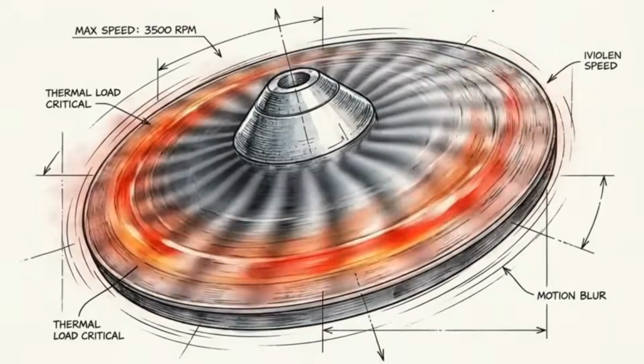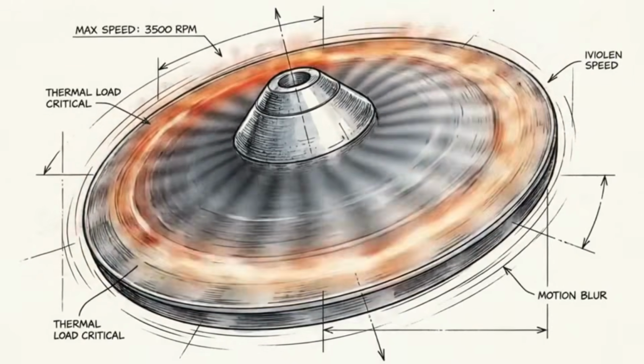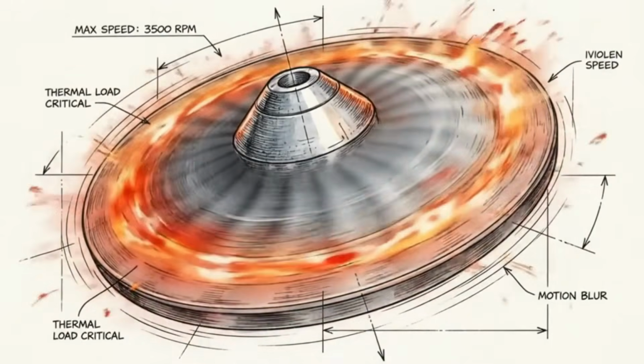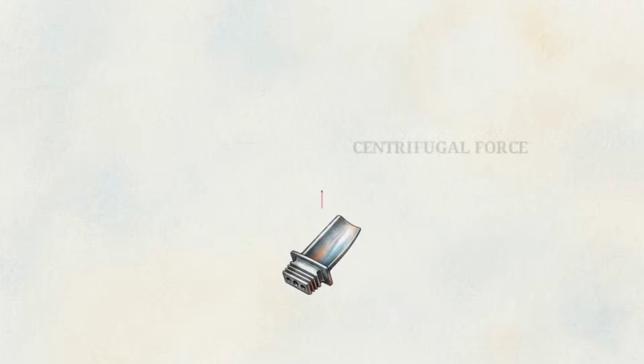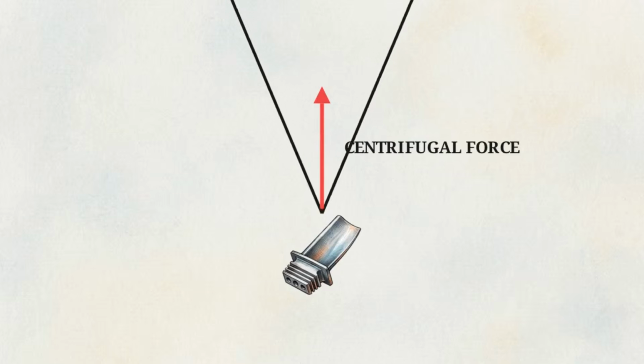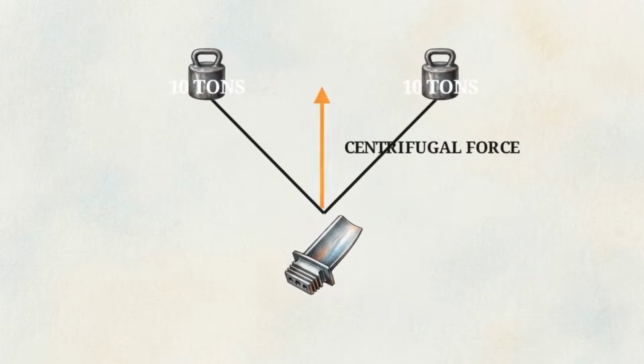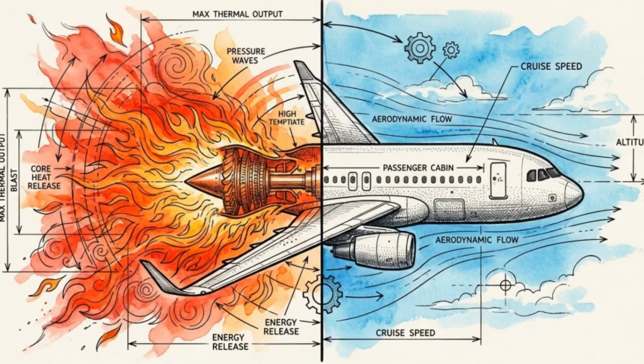Inside that core, hundreds of glowing hot turbine blades are spinning at 12,500 revolutions per minute. At that speed, the centrifugal force trying to rip a single 300-gram blade apart is equal to the weight of 20 metric tons. Engineers are caught in a brutal trap.